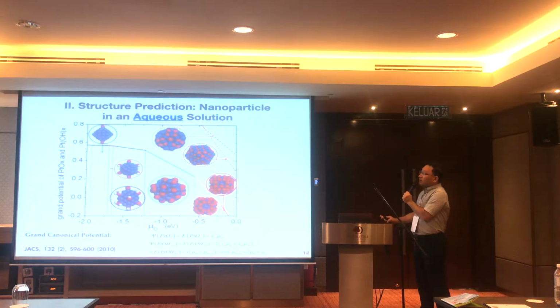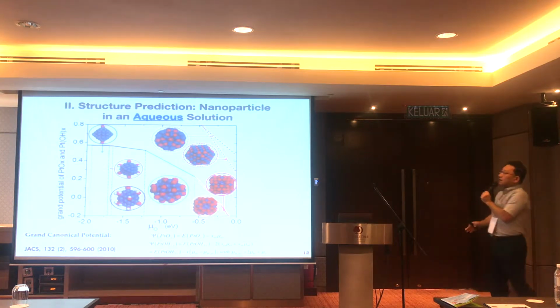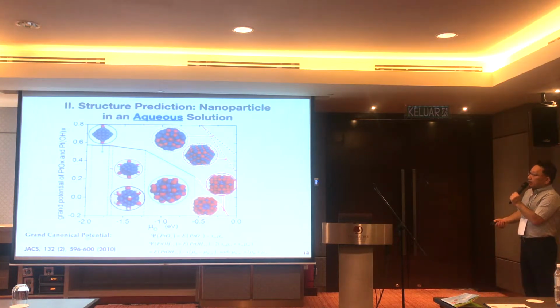We can screen out most of the different topologies, and we can screen out the most stable structure as a function of oxygen partial pressure. Here, this picture shows that at very low oxygen concentrations you can have a very clean nanoparticle. But if you increase oxygen partial pressure, platinum does oxidize.